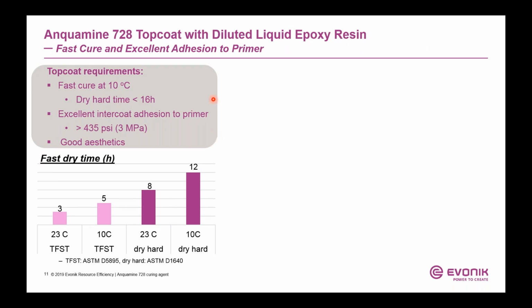So at 10C, as long as it's dry within 16 hours, it can mean a one-day flooring system, and should have good adhesion to the primer and also have good aesthetics. So here I'm going to show you the fast dry top coat and then fast property build up.